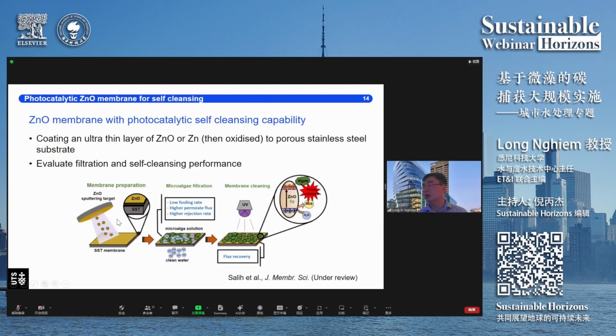So what we have done is we then switch gear. We look at how we can coat a zinc oxide layer onto the membrane. This is a fundamental study. So instead of using a large submerged membrane, we use a small membrane sample. I should note that the membrane sample we use in this part is only 1 centimeter square. That would allow us to effectively deposit zinc oxide onto the membrane surface in the lab.